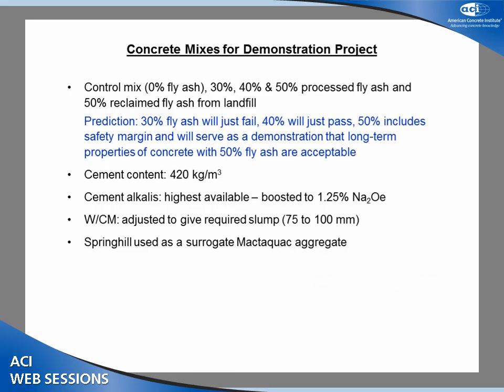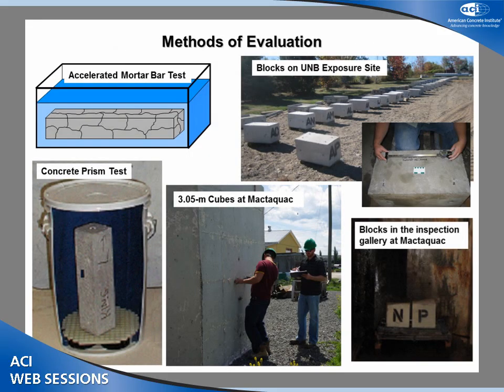And they paid for that. So anyway, they did some mixes for the demo. They did high cement content, boosted the alkalis, but looked at ash at 30, 40, and 50% to see if they're going to build this new replacement dam, whether it'll work or not.